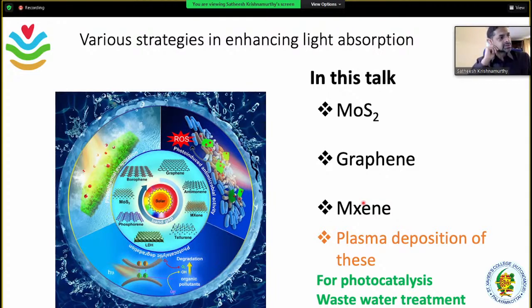When I was doing my PhD, 2001 to 2004, graphite pencil, that is what graphite is. Lead based. Lead it came from a Greek word. Okay, but it is not lead actually. It is graphite. And when I was working on surface science to understand the properties of graphite, we completely cleave it flat. We roll it with cellophane tape and cleave the graphite, and part of it is shiny material. We don't even realize what the shiny material is. We put that in the bin and then make the graphite flat, and then we do the deposition. So that thing which is shiny, which we put in the bin, that was discovered to be graphene, the lightest and thinnest material.